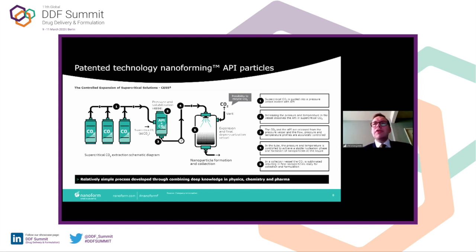Consistency and reducing variability is very important for pharmaceutical production. So we wanted to introduce a controlled process with very good control of the crystallization event. This small pressure drop is enough to initiate nucleation in the line, and then we atomize that — a bit like spray drying — into a collection chamber. In that atomization event, the droplets expand as a nanonuclei suspension of API that rapidly freezes around the API particle, forming what looks like snow in the collection chamber.